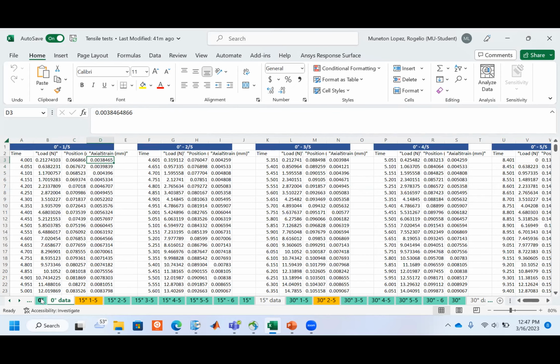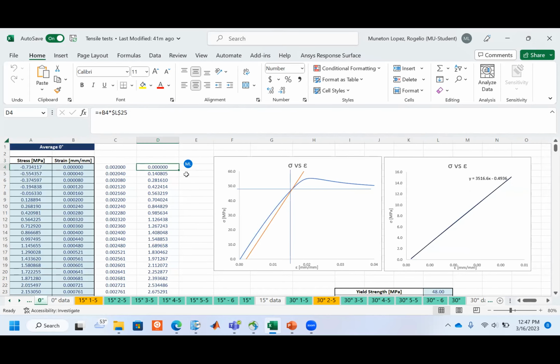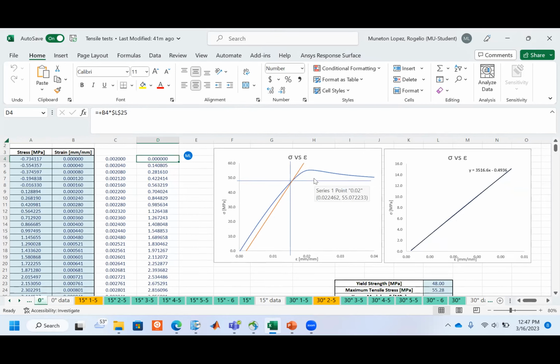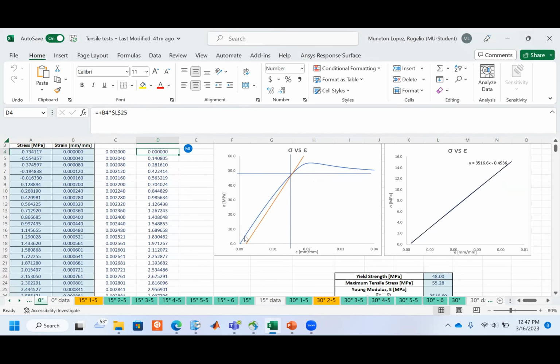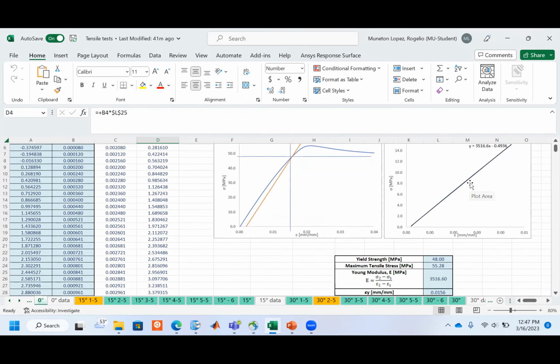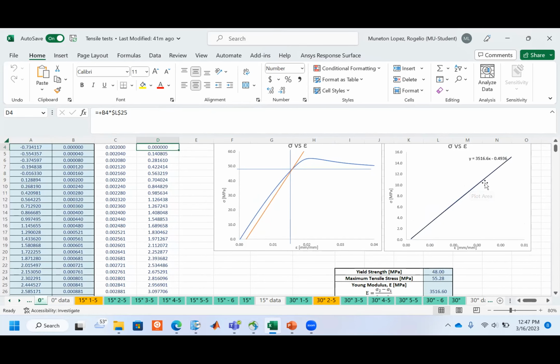So this is the data that I obtained from the machine. I can process that data, and from that data, I can obtain my stress versus strain curve. And from here, you can see that this material clearly has a linear part, so I can use this linear part to obtain the Young's modulus, as you can see here in this figure.